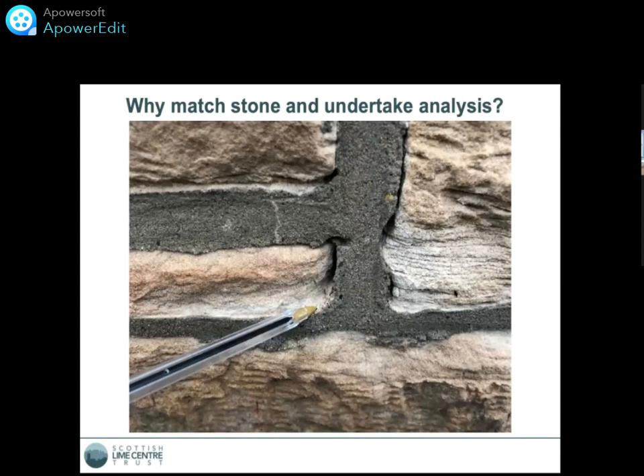And if you look here, you can see these stripes in the rock. Now, these are actually those carbon rich darker layers that you saw previously in the image of the really weathered stone, except this stone is the other way. And you can see where you are getting preferential weathering, because obviously it's in contact with this hard cement and this is a very soft stone, particularly in these corners where more water is going to flow or get trapped, you end up with this decay.